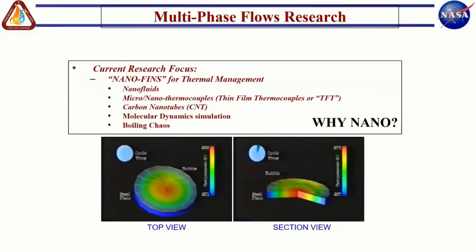So coming back to this whole idea of leveraging cold spots, we decided to make nano thermocouples, or what we call thin film thermocouples, to study these cold spots, both in the presence of these carbon nanotube coatings as well as in the absence of these carbon nanotube coatings. And having these nano thermocouples actually gave us a lot more insight into these length scales and time scales, because we were able to couple it with molecular dynamic simulations as well as boiling chaos models. And I'll come to that in a minute.